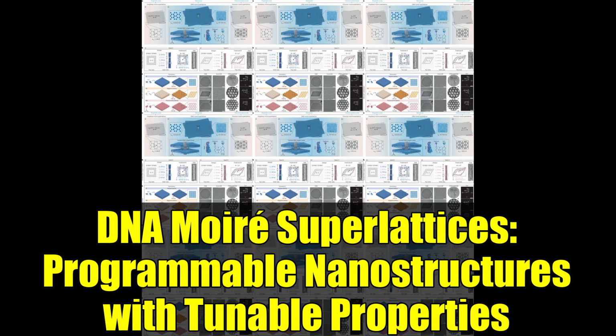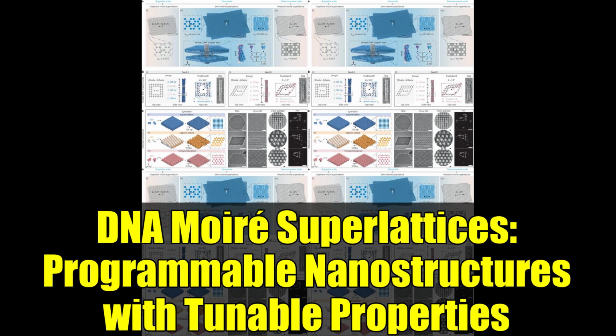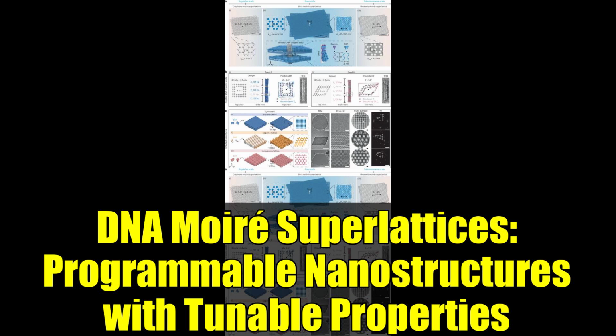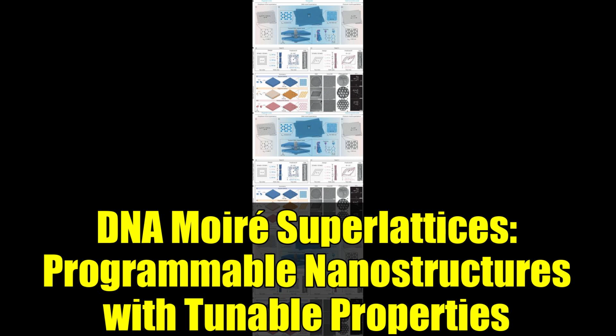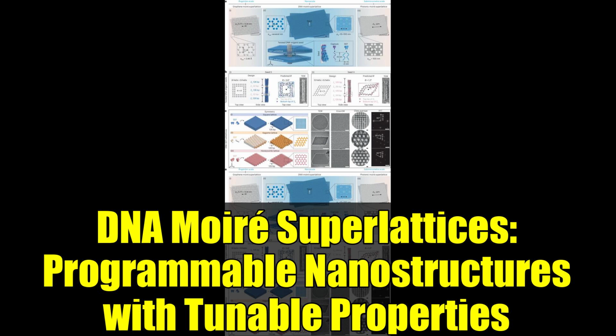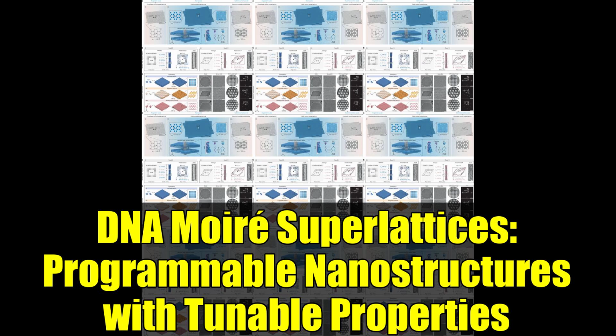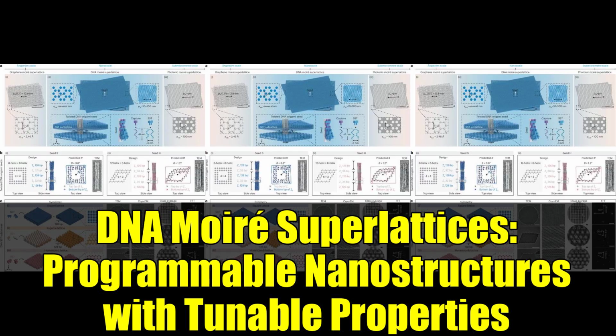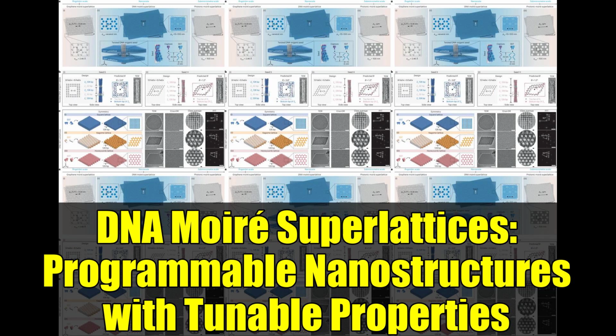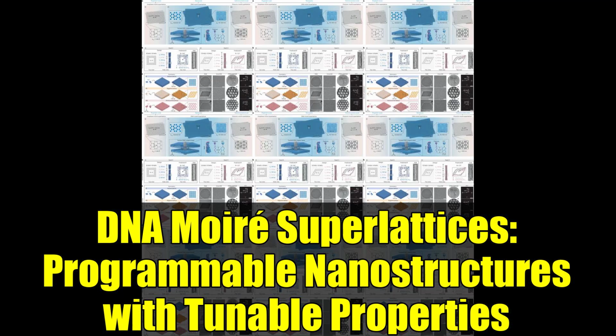The researchers didn't stop at bilayers. Armed with their modular framework, they constructed trilayers, hybrid superlattices, mixing, for example, square and kagome, and even gradient Moiré structures. These latter ones stand out. By employing an asymmetric, trapezoidal DNA seed, they induced a gradual shift in lattice orientation across a DNA layer, creating a gradient in Moiré periodicity, a feat rarely observed at this scale. If you think about a rainbow's gentle change in color across the sky, that's what's happening here at the nanometer level, but with DNA tiles instead of light.